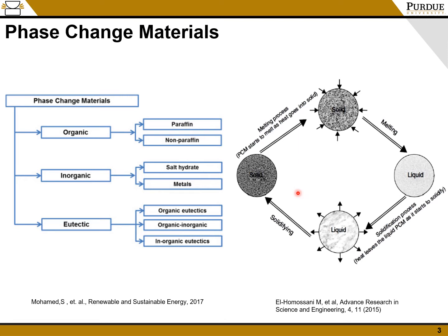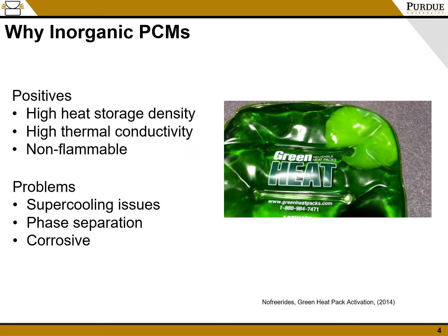There's a lot of different phase change materials, main categories being organic, inorganic, and eutectic. And for the purposes of this study, I focused on the salt hydrates because of their particular set of properties that were intriguing. The main positives of inorganic PCMs that make them a desirable material are their high heat storage density, higher thermal conductivity than organic PCMs, and the fact that they are non-flammable, unlike organic PCMs that are flammable. However, they have significant problems of supercooling and phase separation, as well as being corrosive, and all those problems need to be tackled in order to improve their utilities.